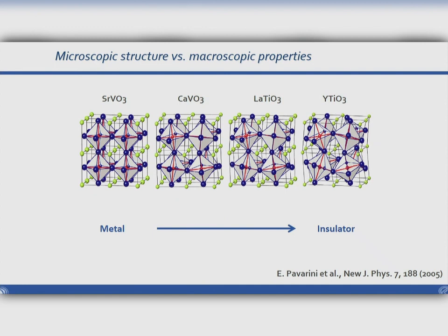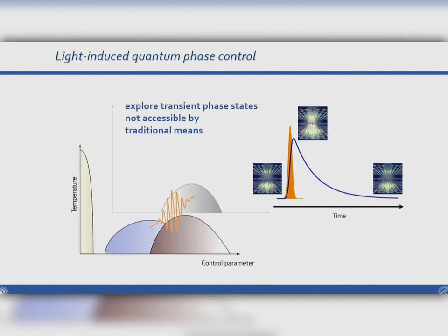You have tilts and rotations, and then the bonds are no longer straight, and it's much more difficult for electrons to do electronic transport. So therefore, they go from a metallic to an insulating behavior. But at the same time, they also change their magnetic properties. While these two are paramagnets, this one is an antiferromagnet, and this one even becomes a ferromagnet. So structure is really important, and that's why we want to control the structure to change the functional properties of these materials.